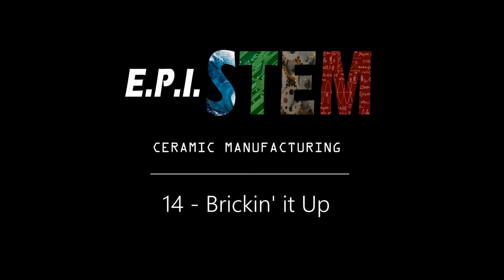So in this case, replace the bread with a little precursor pre-ceramic powder and replace the heating strips with carbon paper. This carbon ceramic sandwich is really all there is to the UHS process. The magic behind it all is really just in how quickly the carbon strips can reach the ultra high temperatures necessary and transfer them to the precursor to create that sample. One of the benefits is that you can squeeze a lot of these precursors into the carbon strips at once, so you can process multiple at a time.